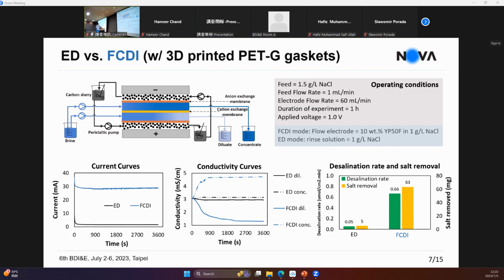And we performed the experiment under exactly the same conditions. The only difference was that in FCDI mode, we use flow electrodes. In electrodialysis, we use sodium chloride solution as electrode rinse solution. And as you can see here in the results, the FCDI clearly outperformed electrodialysis. The current values were much higher. Here you can see that the conductivity of the diluted stream was much lower for FCDI than for electrodialysis, and obviously it means higher desalination rate and higher salt removal. So the first impression was that, okay, it works. We can use a 3D printed gasket instead of graphite current collectors.